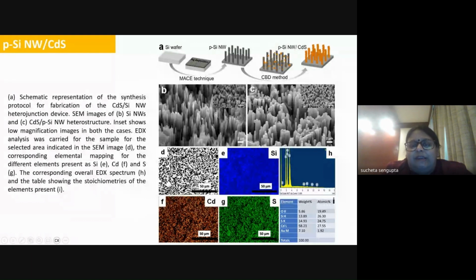These are the same images. On B, it is the pristine silicon nanowires, and C is the silicon nanowires after coating with cadmium sulfide. If we do an EDAX of that, we can see that the cadmium sulfide is present almost in the stoichiometric ratio and uniformly distributed over this entire area, which shows uniform coverage of the individual silicon nanowires.